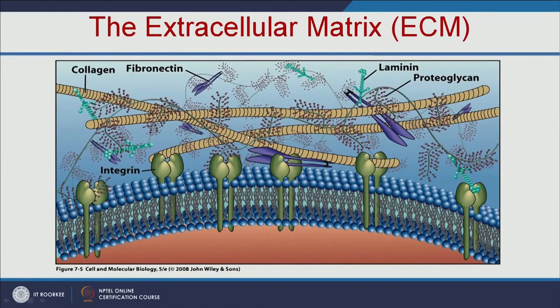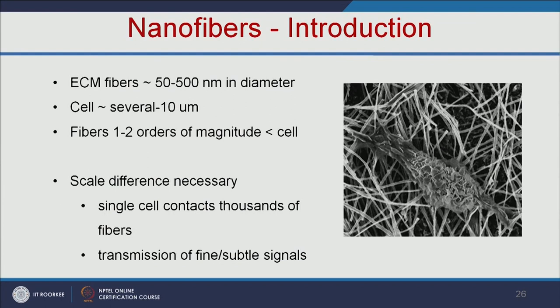The extracellular matrix is present in each tissue and organ, and all cells attach and grow on top of it to form tissue. Nanofiber-based scaffolds exactly mimic the extracellular matrix. The extracellular fiber matrix has a diameter in the range of 50 to 500 nanometers, while cell size is between 10 to 100 micrometers. As seen in scanning electron microscope images, a single cell can bind to thousands of nanofibers, enabling fine signal transmission.